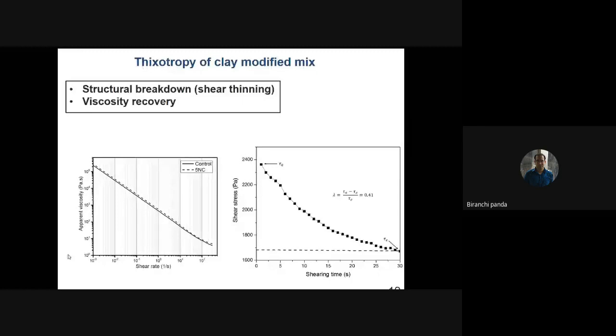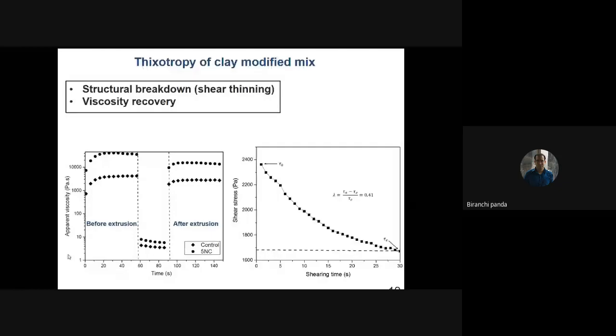Now, since printing is not only about extrusion, we need to deposit more layers. So now let us come to the third part of the test, that is called viscosity recovery. Because during pumping, you might have applied a very high shear rate and the material completely loses viscosity. Now, if the same material is deposited, we cannot print more layers. We now need the same material to recover its original viscosity, and only then can we print more layers. So for that, we conducted a viscosity recovery test. In this test, we investigated the state of the material after pumping or extrusion. We conducted the viscosity measurement at three intervals: before extrusion, during extrusion, and after extrusion.